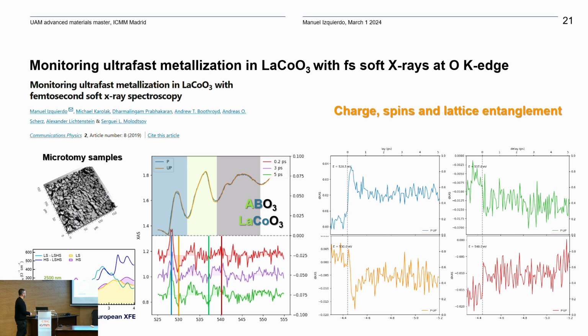So the idea is that if you measure the oxygen K edge, you are able to understand all that is going on in the system. You can understand the electronic properties, the spin properties, and also the structure. There is the proof of principle we did here using femtoslicing, and what we wanted to do is an experiment in a free electron laser because you have higher fluence, and then you can study in more detail the fluence dependence and other things.